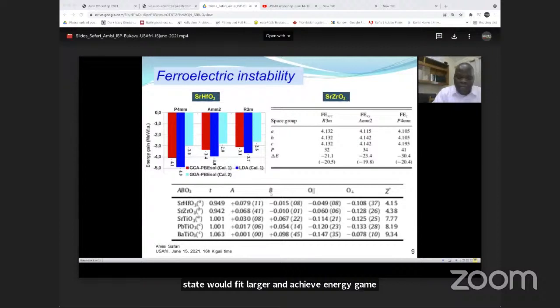Another striking fact is that when we calculate the atomic eigendisplacement of the polar instability, when we consider the titanate perovskite here in the cubic phase, the eigendisplacement vector of the polar instability is dominated by opposite displacement of B and O atoms, while for the FD perovskites here, hafnate and zirconate, the B and O displacement contributions become smaller, and at the gamma polar instability, the B atoms appear to move now, not against, but with the oxygen atoms.